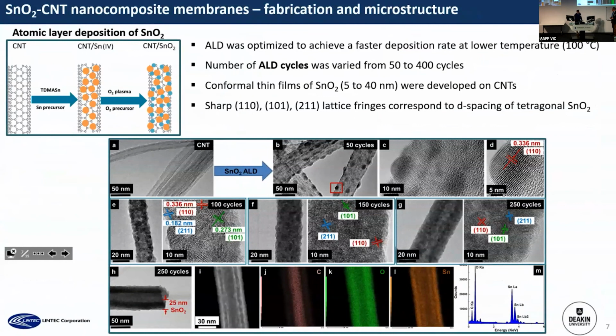And when I measure the thickness here, it was also around 25 nanometer, matching the measurement that I have done using the ellipsometric technique at MCN, which means that with using this technique, we can have a precise control over the thickness.